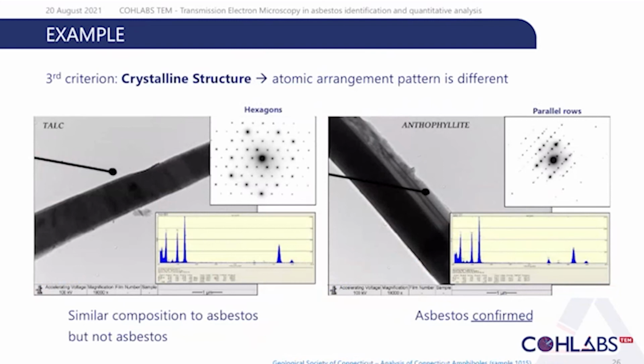So for this same example, as you can see, the fiber on the left has a hexagon pattern for its crystalline structure, while on the right you have parallel rows, and that's typically what we are expecting from an asbestos fiber, to have those parallel rows. So thanks to this third criteria, you can unequivocally identify anthophyllite on the right, compared to a fiber of talc on the left.